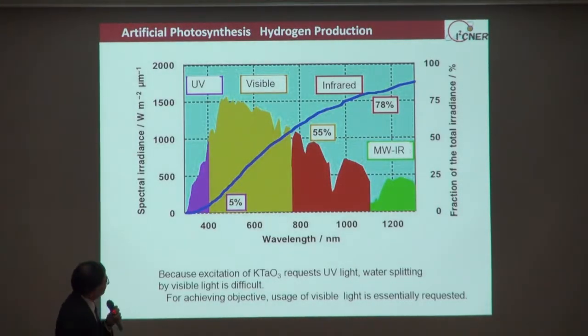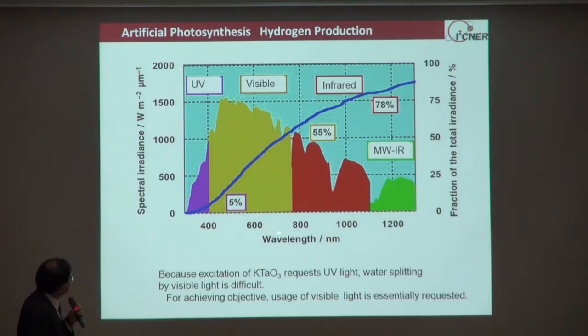And then the reason why the conversion efficiency is small, although we achieve a large separated state. And this is the UV light. This is the frequency of the sunlight, and this is the conversion efficiency. This means if we use 100% of the UV to the electricity, the conversion efficiency is like 5%. And if we convert visible light, then the conversion efficiency is around 55%. And the current catalyst is used at this level. Therefore, the ratio of the energy in the solar light is very small. That is why the conversion efficiency becomes very small.